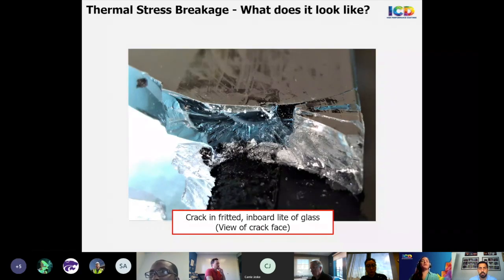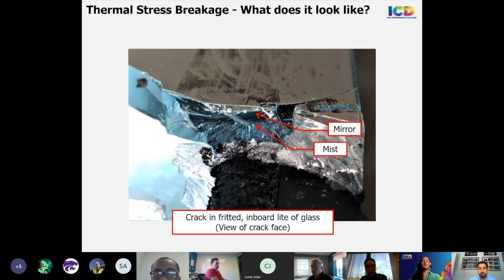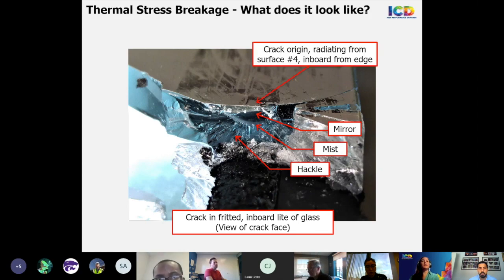So basically what I'm doing here is just showing visual characteristics of glass that has been broken due to thermal stress. So now we're looking at the face of the crack on one half, and there are components that tell us this is the origin. First, there's a semicircular shape referred to as the mirror. Outside of the mirror, there's a fine pebbled area known as mist, and following that's a jagged radiating pattern known as hackle. So collectively, this tells us that the crack began up at the top on surface 4 where the frit is applied and radiated downward to the left and to the right.